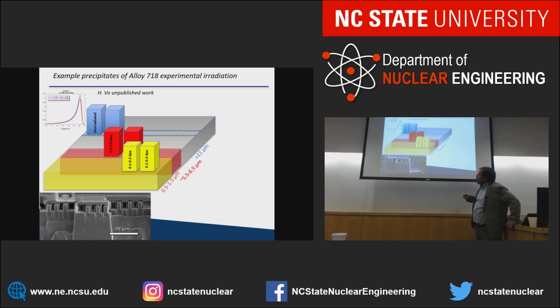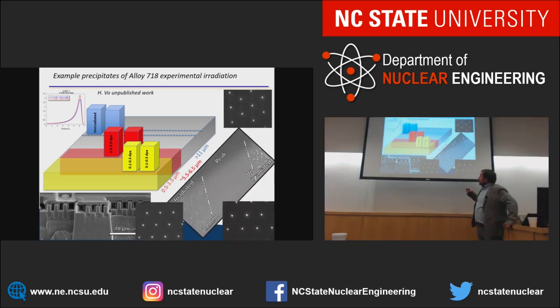And here's again our pillars. And we compress them. And so now we look in the TEM across this length, and we have the irradiated thing. And we can see these little dots here. Those are the precipitates. And they're much smaller than in the unirradiated region. Unirradiated has pretty large ones, relatively speaking, and the irradiated one has small ones. Where my stopping peak is, I have none. Well, the stopping peak has a much higher dose than the unirradiated region. And therefore, these large precipitates dissolve more and are completely dissolved at some point.